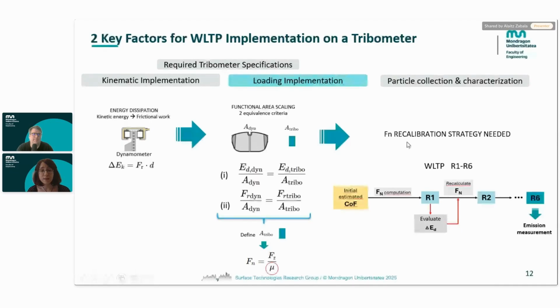Accordingly, we need a recalibration strategy for the normal force. And here we do have a scheme showing the steps that we follow in our system. We start with an initial estimated coefficient of friction, and later on, during each of the repetitions of the WLTP cycle, we evaluate the real dissipated energy and we recalculate the normal force accordingly. And we repeat this step over all the repetitions, so that by the time we reach repetition number 6, at which the emissions are measured, the dissipated energy is very close to the target one.